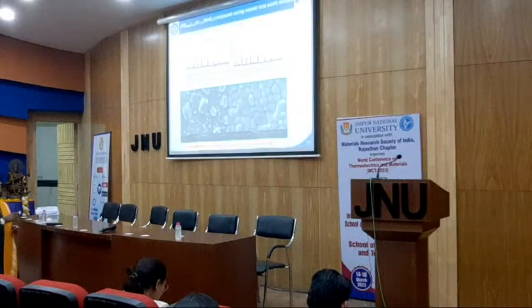Then we took these commercial materials. We made two sets of compounds, the same rare earth mix, one this set and another this set. This set is exactly mimicking the natural resources, and another set is without the cerium, to show them that this does not have any magnetic property. So when we did both and checked the samples, next please, we see what has happened.